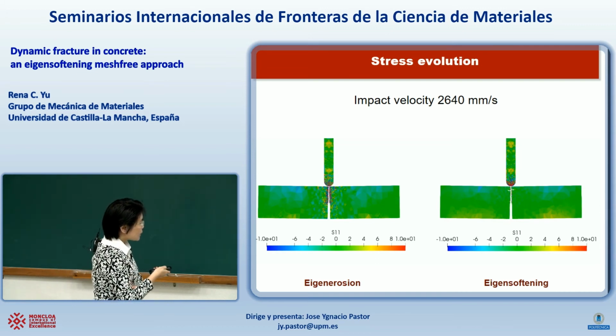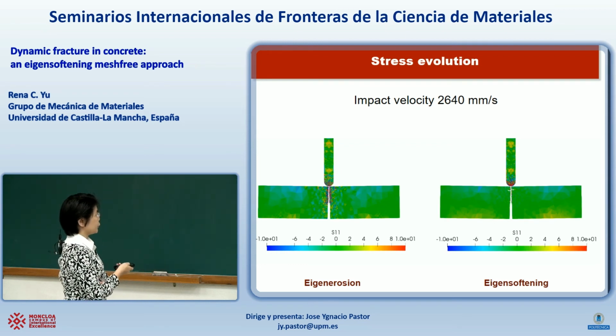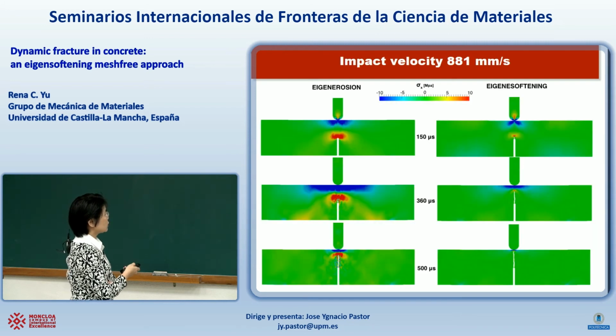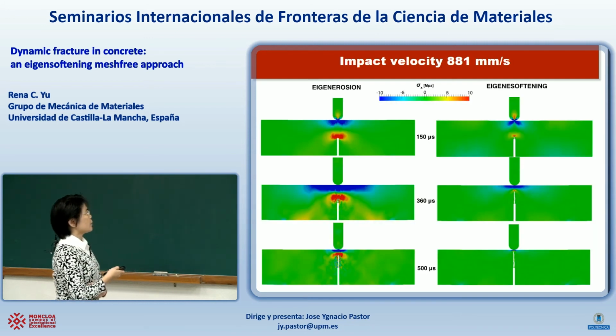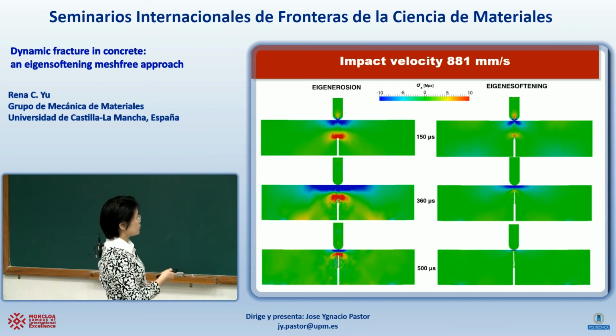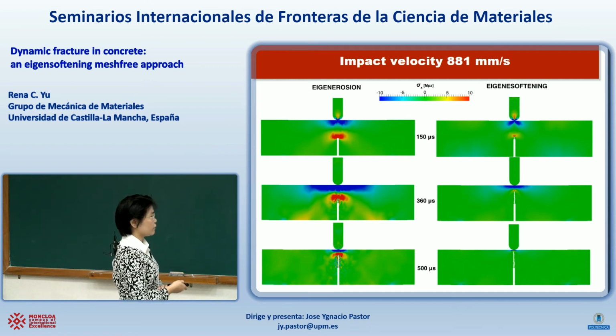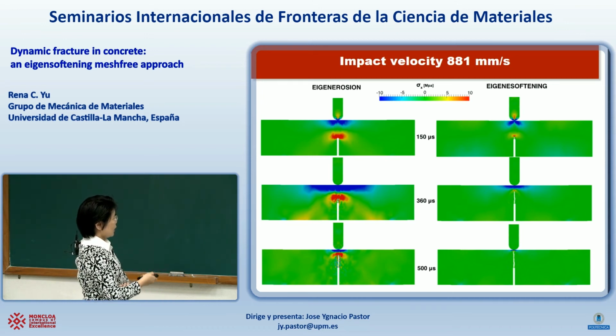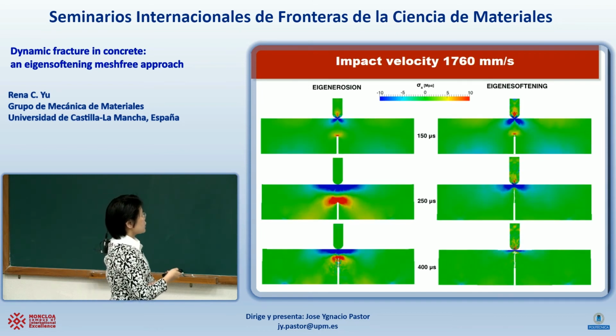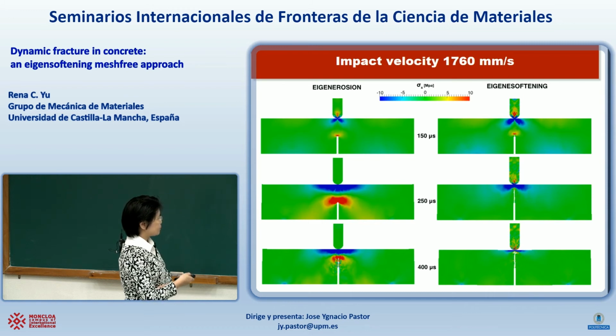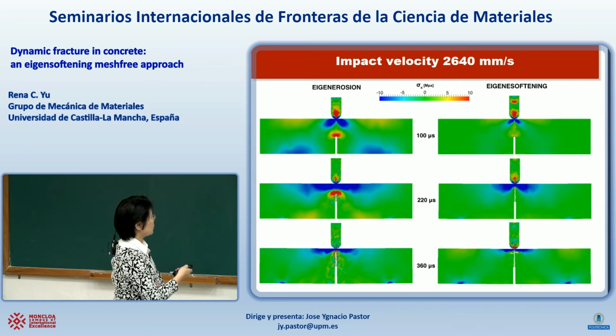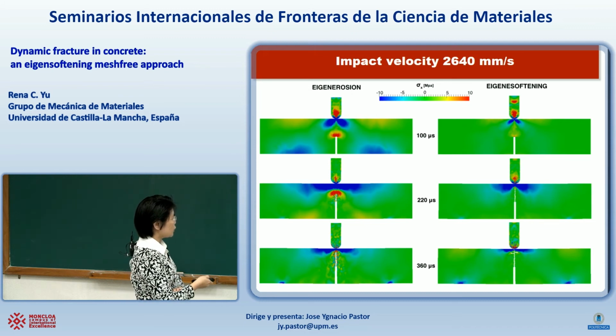So we also see there's a small branch if we use our eigensoftening approach. So I'm going to show 3 snapshots. If we look at 3 different velocities, this is the minimum one, which is 881 millimeters per second, for the loading times of 150 microseconds, 360, and 500. What you see here is that in all 3 cases, you have a big stress concentration. The following velocity, we see something similar, but here we already see some small branches, and this is the one corresponding to the video. We have 2 branches here.